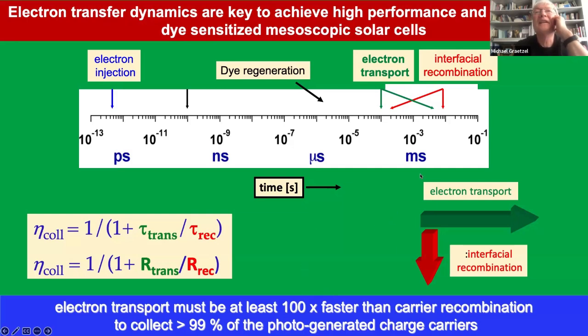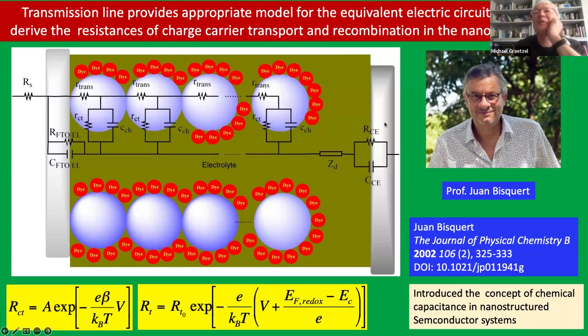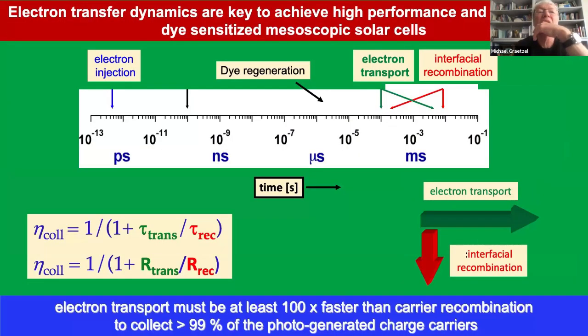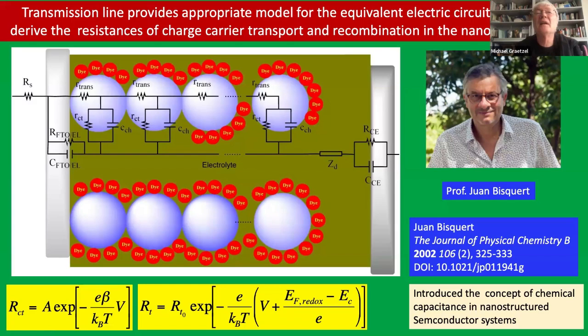However, we analyzed by impedance spectroscopy using the transmission line model developed by our colleague, Professor Juan Bisquert, who is now a professor in Valencia. We could determine those resistances easily. That was really a very important study that Professor Bisquert initiated. So these resistances could be measured, and then we could determine the transport and recombination time of electrons, and that gives the collection efficiency. So finally, it's easy enough to say if the transport is 100 times faster than recombination, then we will collect all the charge carriers, 99% at least.